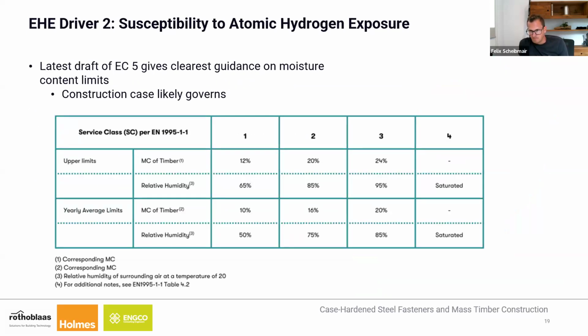If we look at moisture content levels and how we best design those, then really the latest iteration of the Eurocode, which is currently in draft, is the best place to look. Like I said before, we're not looking here at the end use of the building most of the time, because generally when we're designing a standard timber building, we're likely to be in internal service class 1. But we're looking at the moisture that's likely to be affecting those fixings during the construction phase. So oftentimes we'll be in that second service class, and you can see there's some upper limits of 20% for the moisture content and yearly average limits of 16%.